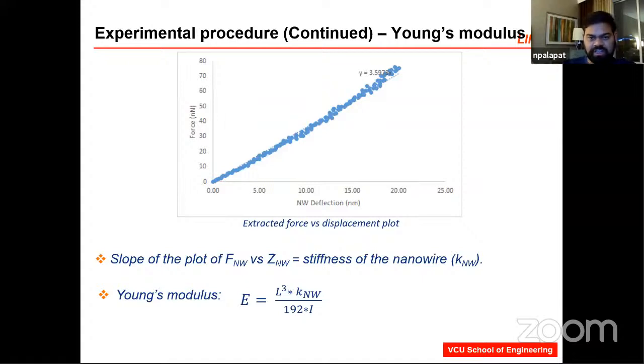Now it really looks so simple, but measuring the nanowire diameter even to the single nanometer can make a big difference in your Young's modulus calculation. So it really depends on how accurate you are able to measure the diameter of the nanowire. Now, further, nanowires are one-dimensional structures. They don't behave the same way as we think they do.